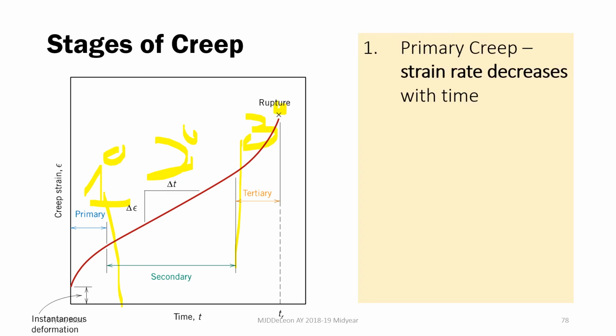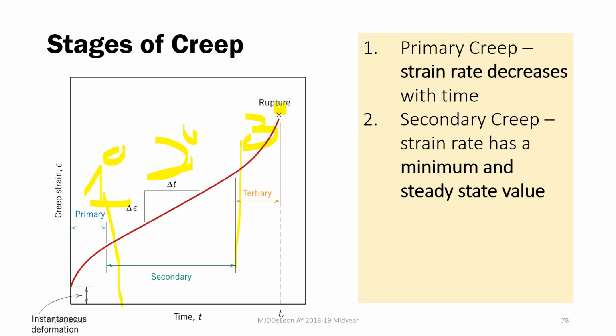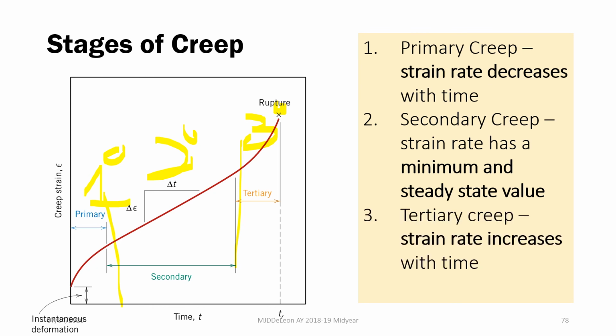So the primary creep, makita natin your strain rate decreases with time, to such a point na mag-equalize siya, at which you would undergo secondary creep. So secondary creep is where your strain rate is a steady state value and it's minimum. And after which, mag-rupture na yung material mo after undergoing tertiary creep, in which the strain rate increases with time. So, creep, fatigue, fracture, and our other failures of our materials, this will be further explained in your MatE 171.